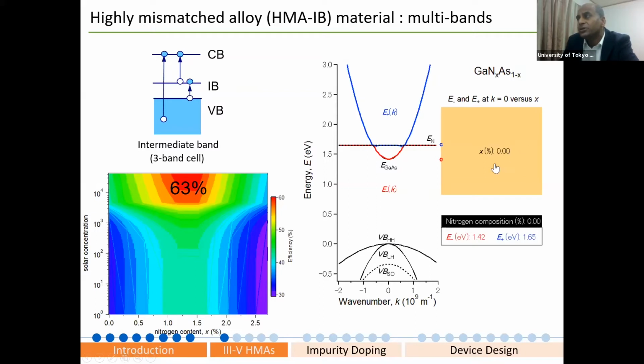So here the nitrogen concentration is 0%. This is just a theoretical calculation. And if you put some amount of nitrogen, then you see the conduction band is split into two bands. One is the E plus band, another is the E minus band. And this is 1% of nitrogen, okay? And now you have three band gaps: the first band gap, the second band gap, and the original third band gap. If you change the nitrogen more and more, you can play with the band gaps.